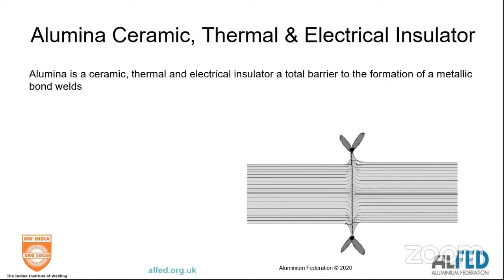When you weld, you go back to very basic theory. What you do is produce a metal to metal atomic bond, and you've got a ceramic oxide. So you need to remove it. You need to either push it out, exude it, or melt it out.